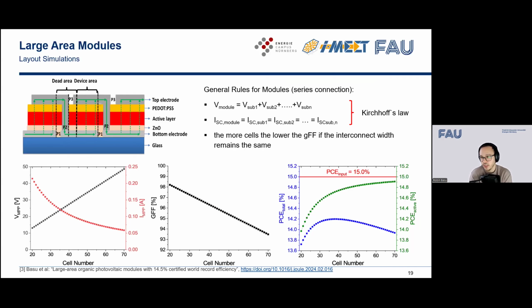And also with each subcell that we add, we add an interconnect to make our charges recombine within it. And that changes the amount of the actually active part of the devices that give out power and current. And that's determined by the geometric fill factor. So the higher the geometric fill factor, the higher the fraction of active area on your given device area.